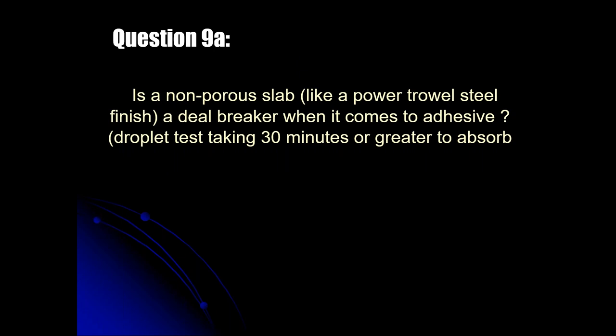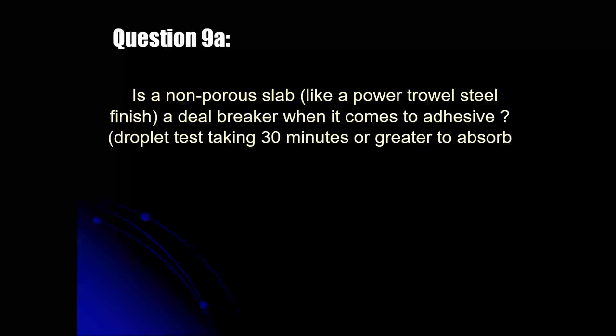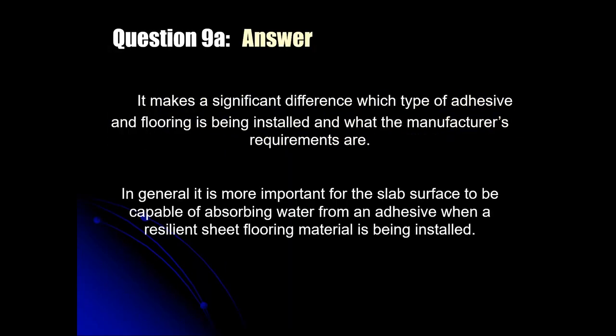Question 9: Is a non-porous slab, like a power trowel steel finish, a deal breaker when it comes to adhesive? Droplet test taking 30 minutes or greater to absorb. It really makes a difference as to what type of adhesive and what type of flooring installation is going to take place. For a VCT tile or dimensional tile installation, if you're using a water-based acrylic adhesive, yeah, it would be helpful for the surface to have a degree of porosity, but because we can stand back and let a fair degree of the free water in the adhesive evaporate before we have to lay in the tile and roll it, we've got some greater latitude than we do if we're doing sheet goods.